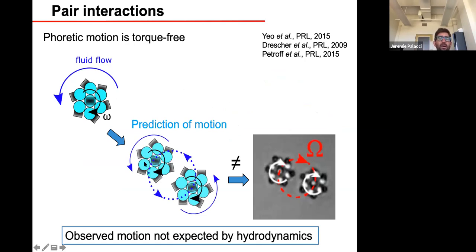It's a big one: if you take one of those microgears, because of phoresis, each one of those swimmers is force-free. So we could expect that those microgears would be torque-free. So if they spin that way, it means that on average, the fluid flow has to compensate and go the other way. So now if I put two gears co-rotating next to each other, I indeed predict that they would co-rotate, but in a direction which is opposite to the direction of their co-rotation. And that's opposite to what we see experimentally. So I'm not saying there is no hydrodynamics, I'm just saying that it cannot be the major contributor to what we observe, because it goes the opposite way.